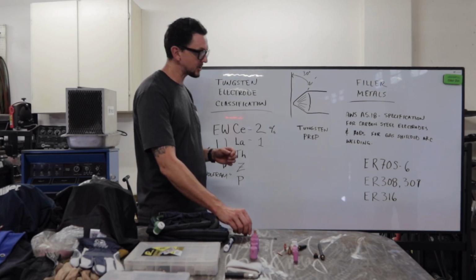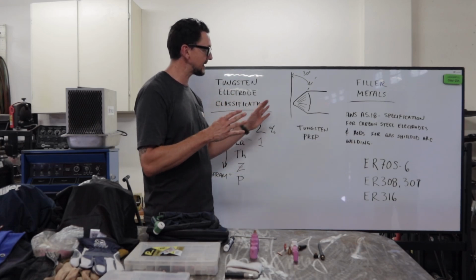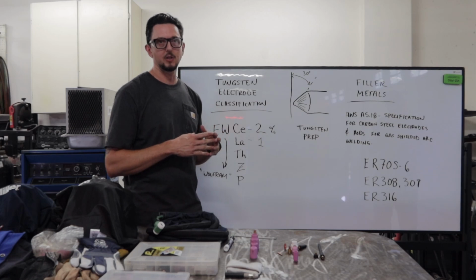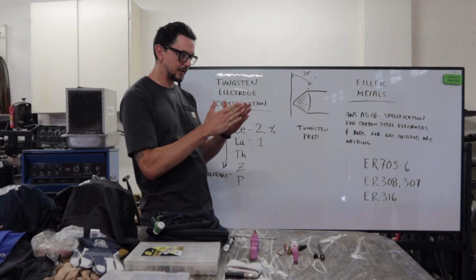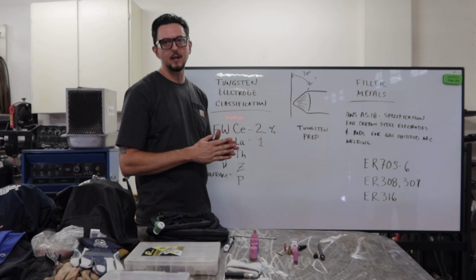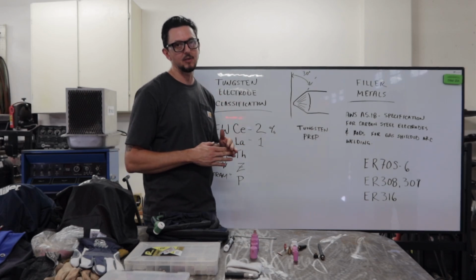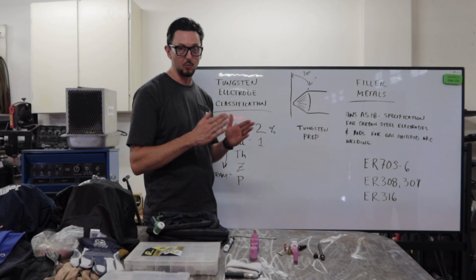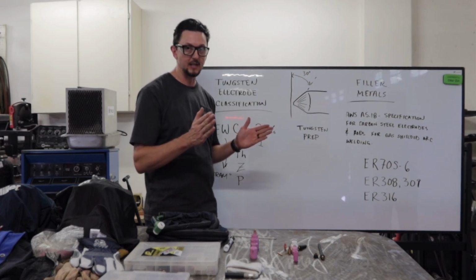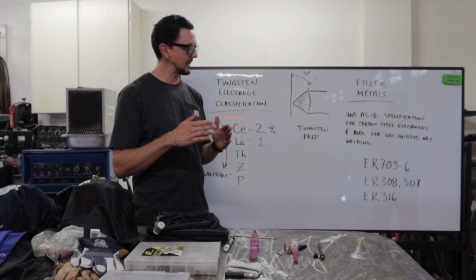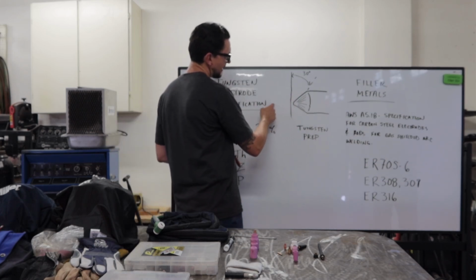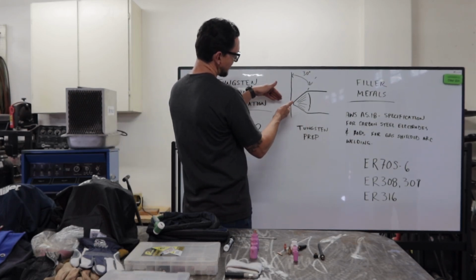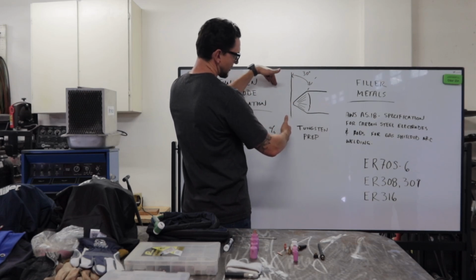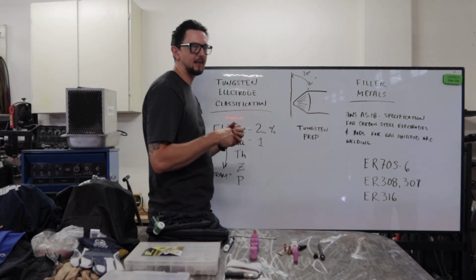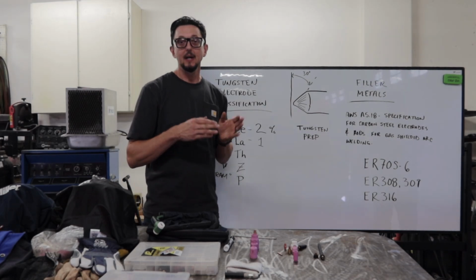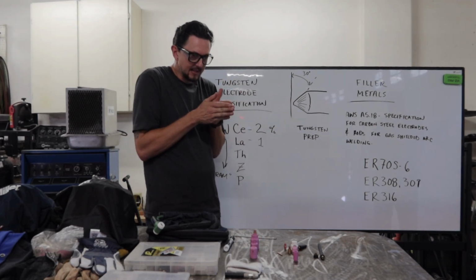Now, beyond this 30-degree bevel, if we want to put an extremely long point on it or a more stubby point, that's going to give you different properties as far as the width of your arc and that sort of thing. It's actually kind of the opposite of what you'd think. If you have a very long point here, then it's going to give you a wider cone. So it's good for, a lot of people like it for open root pipe, so it's not focusing all the heat right in the center of that opening.